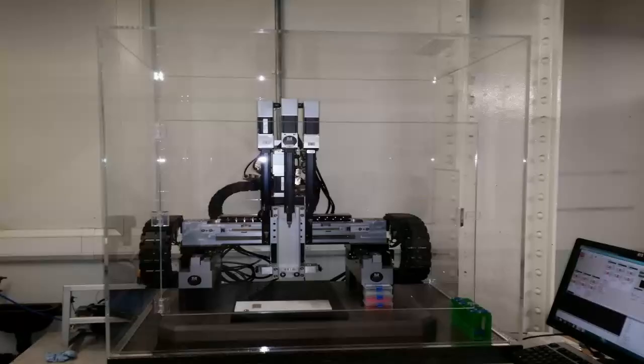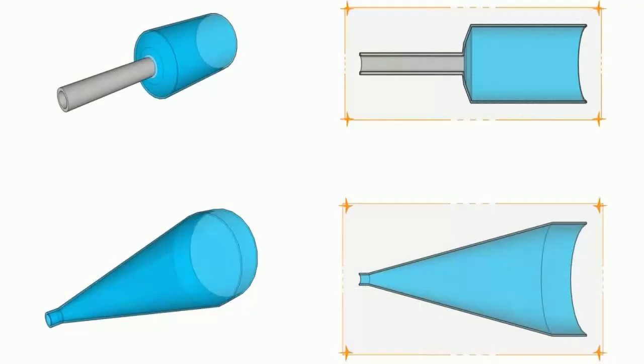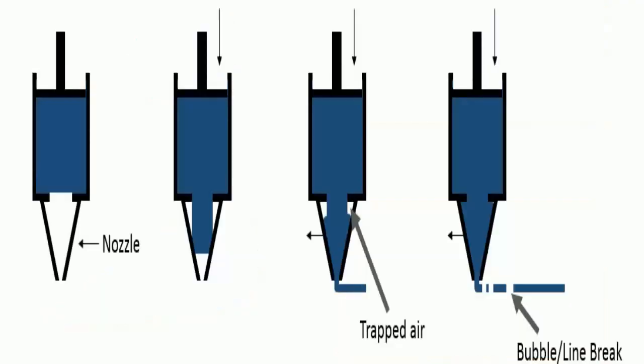How? Well, you mix your ceramic powder into the cold liquid pluronic. That makes it easy to get a smooth, uniform paste without clumps. Then, as you extrude it at room temperature, it naturally warms up slightly and instantly gels, helping the printed filament hold its shape perfectly. That's fantastic, using a weird property to solve a problem. Exactly. It's a counterintuitive property harnessed perfectly for this application.